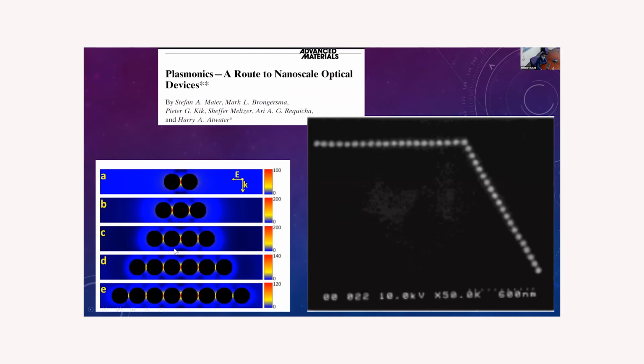For example, when you have a linear cluster, the electric field is located in the hot spot. That goes very well with the idea of Maier, to illuminate some region of this cluster. Due to the nanoparticle coupling, the energy or the light, the near field, will be transferred to the other side.